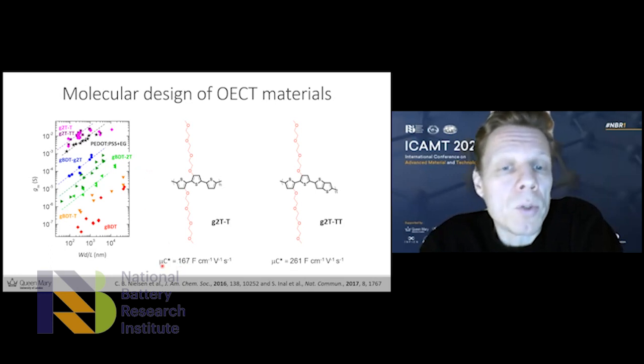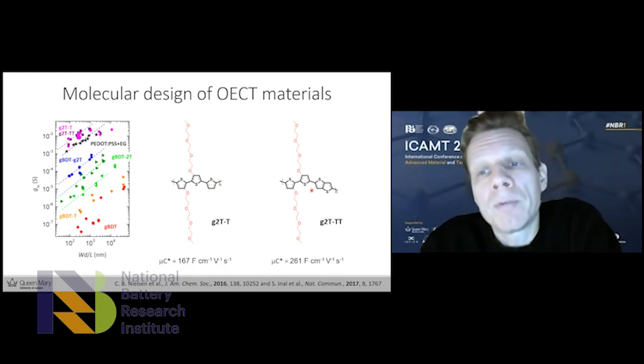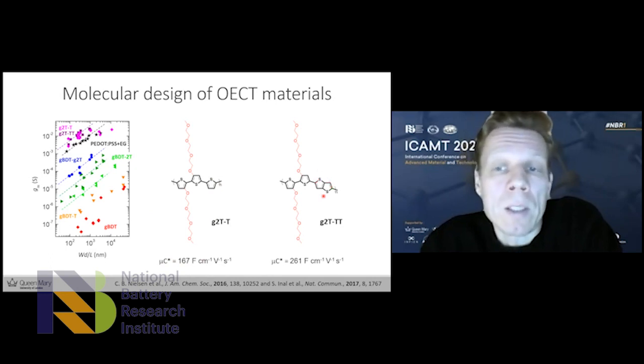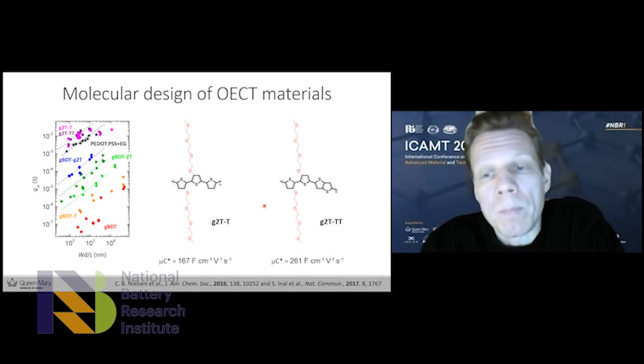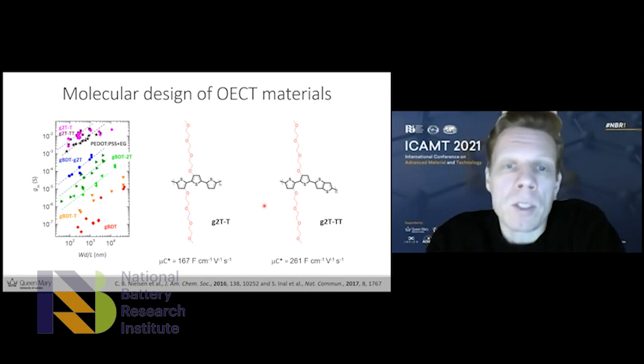I've also listed the mu-C star products that I talked about in the beginning to give you an idea about what a good value is in terms of the mu-C star product. For this polymer here with a thiophene comonomer, we get a value of 167 farad per centimeter per volt per second, and slightly better performing when we have a thienothiophene, a more conjugated extended unit, we get a mu-C star product of 261. So try and keep these numbers in mind as we'll talk about some new materials and see how they compare to these new benchmark materials that we have developed.